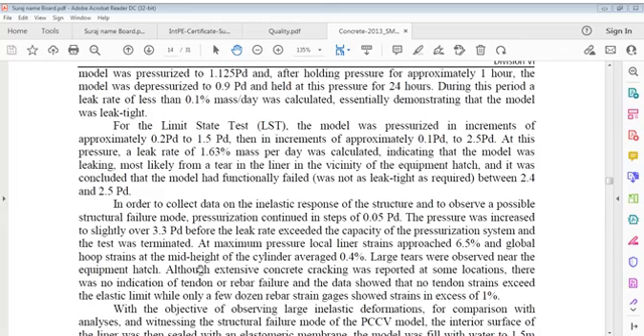The model was pressurized to 1.125 Pd and, after holding pressure for approximately 1 hour, was depressurized to 0.9 PD and held at that pressure for 24 hours. During this period, a leak rate of less than 0.1% mass per day was calculated, essentially demonstrating that the model was leak tight.